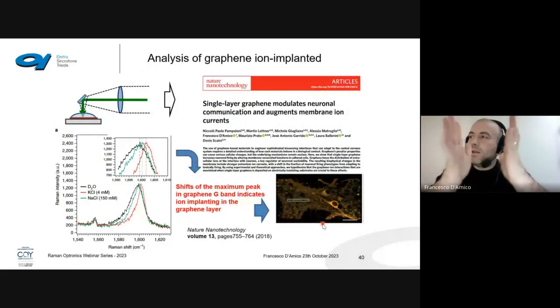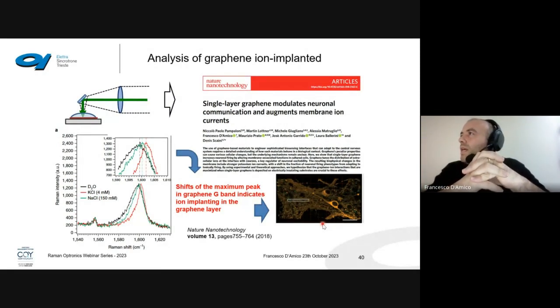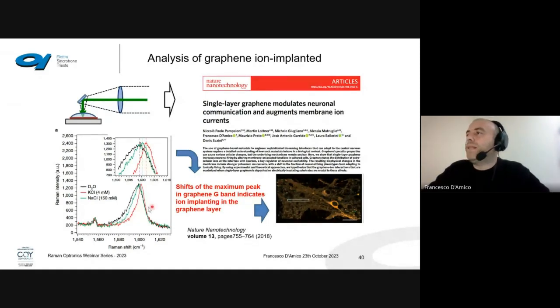Another relatively old experiment. What we have done is the analysis of graphene ion implanted into neuronal growth, and we have seen a shift in the maximum peak of the graphene G band, indicating the ion implanting in the graphene layer. My colleagues recognized a difference in the growth of this neuronal pattern. They suspect that it could be caused by the ion implanting in the graphene layer, but were not able to demonstrate it. By using the high resolution, look at this scale.